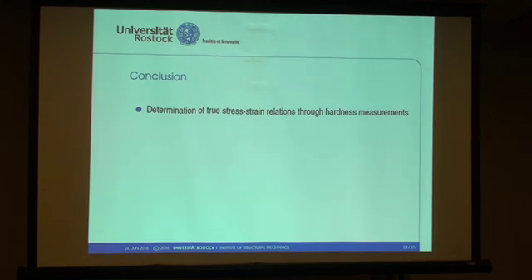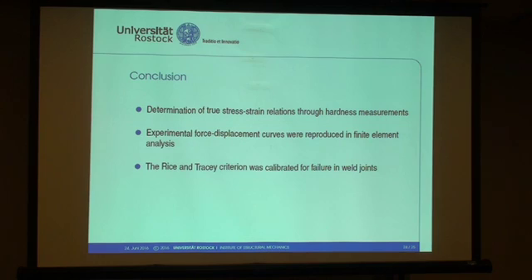First, it was possible to determine true stress-strain relationships from hardness measurements, applying these true stress-strain relationships of the heat affected zone and the weld metal to the finite element model of the cruciform specimen. It was possible to reproduce the experimental force displacement curves of the cruciform specimens. Furthermore, it was possible to calibrate the Rice and Tracy failure criterion, and applying the calibrated Rice and Tracy failure criterion to the finite element model of the tank ship, it was possible to investigate the load capacity of the weld joints between PVPS and bulb profile.